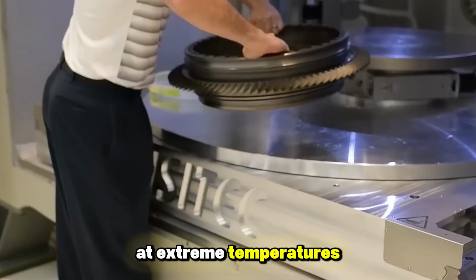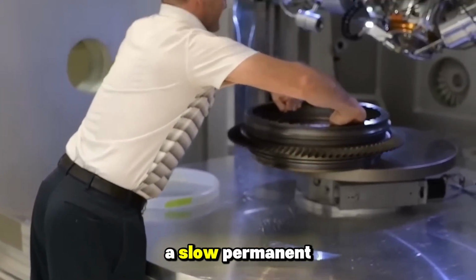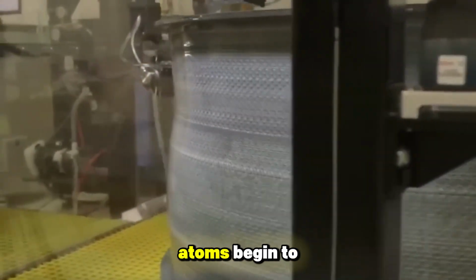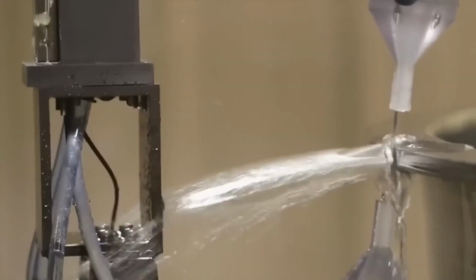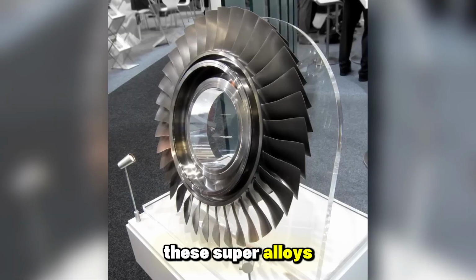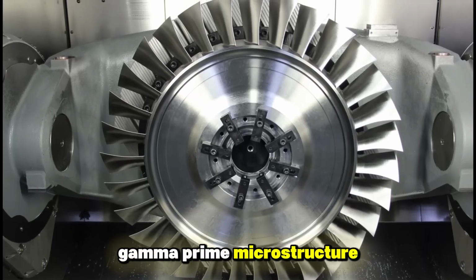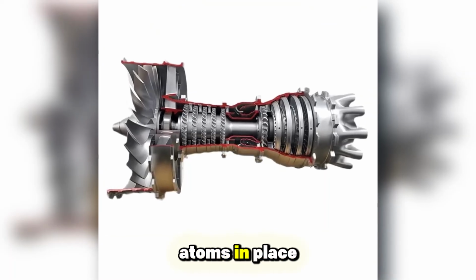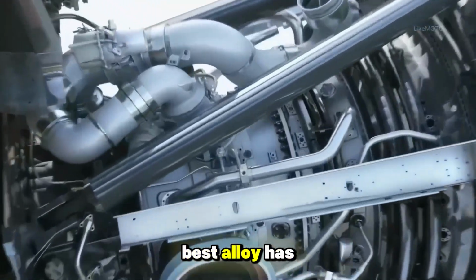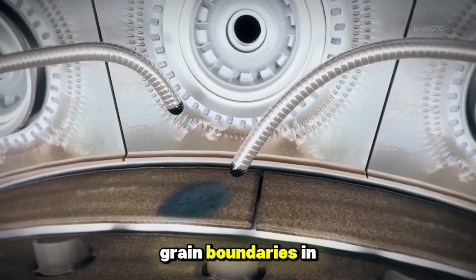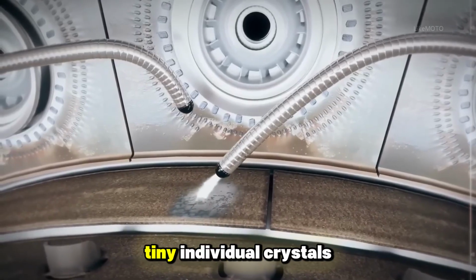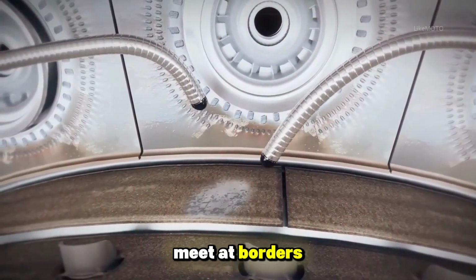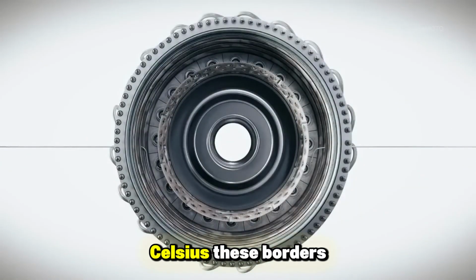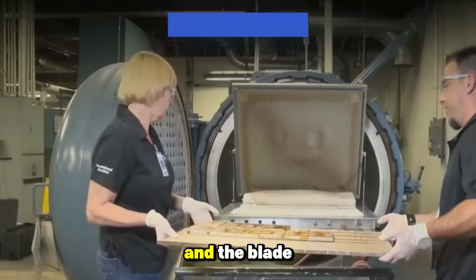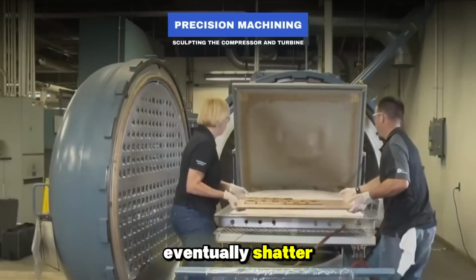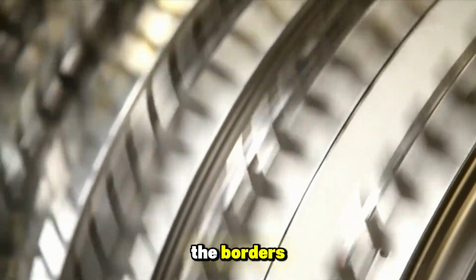At extreme temperatures, most metals suffer from creep, a slow, permanent deformation, where the metal atoms begin to slide past one another. To prevent this, these superalloys are designed with a specific gamma-prime microstructure that locks the atoms in place. But even the best alloy has a weakness: grain boundaries. In a normal piece of metal, tiny individual crystals meet at borders. At 1200 degrees Celsius, these borders become liquid-like, and the blade will stretch and eventually shatter. The solution? Eliminate the borders.